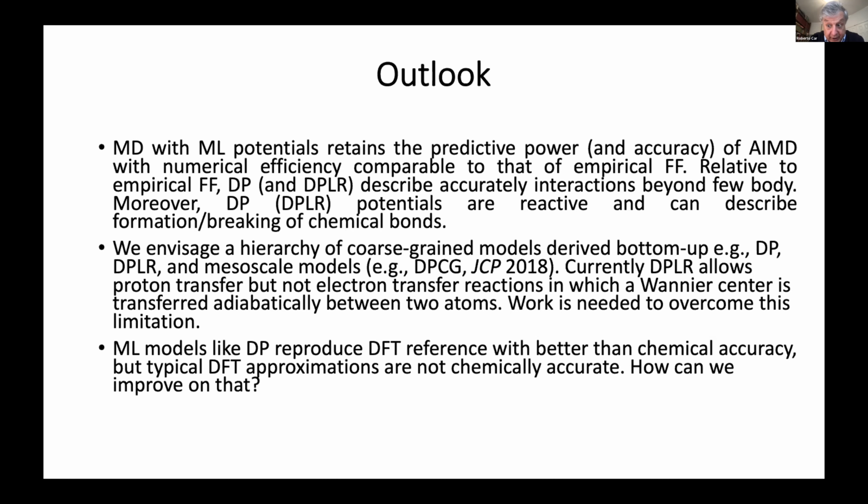Regarding the deep potential long range that I described, because we are using this Wannier centroid, we are just considering the Wannier centers, which are always associated to a particular atom, like the oxygen in this water system. One can describe proton transfer reactions with deep potential long range, but not electron transfer reactions in which an electron or a Wannier center is adiabatically transferred between two atoms. This is something for which there is currently work going on in order to overcome this limitation. But in general, all these potentials are reactive potentials.